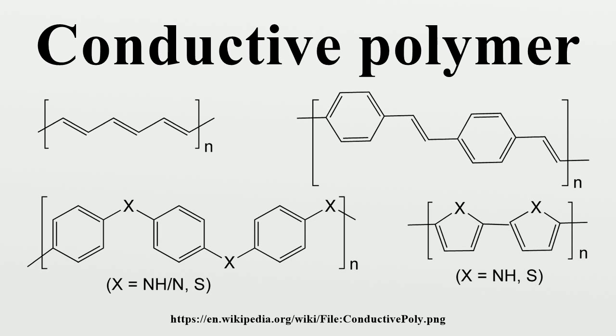Polyacetylene has alternating single and double bonds which have lengths of 1.44 and 1.36 Å, respectively. Upon doping, the bond alternation is diminished and conductivity increases. Non-doping increases in conductivity can also be accomplished in a field effect transistor and by irradiation. Some materials also exhibit negative differential resistance and voltage-controlled switching, analogous to that seen in inorganic amorphous semiconductors. Despite intensive research, the relationship between morphology, chain structure and conductivity is still poorly understood.